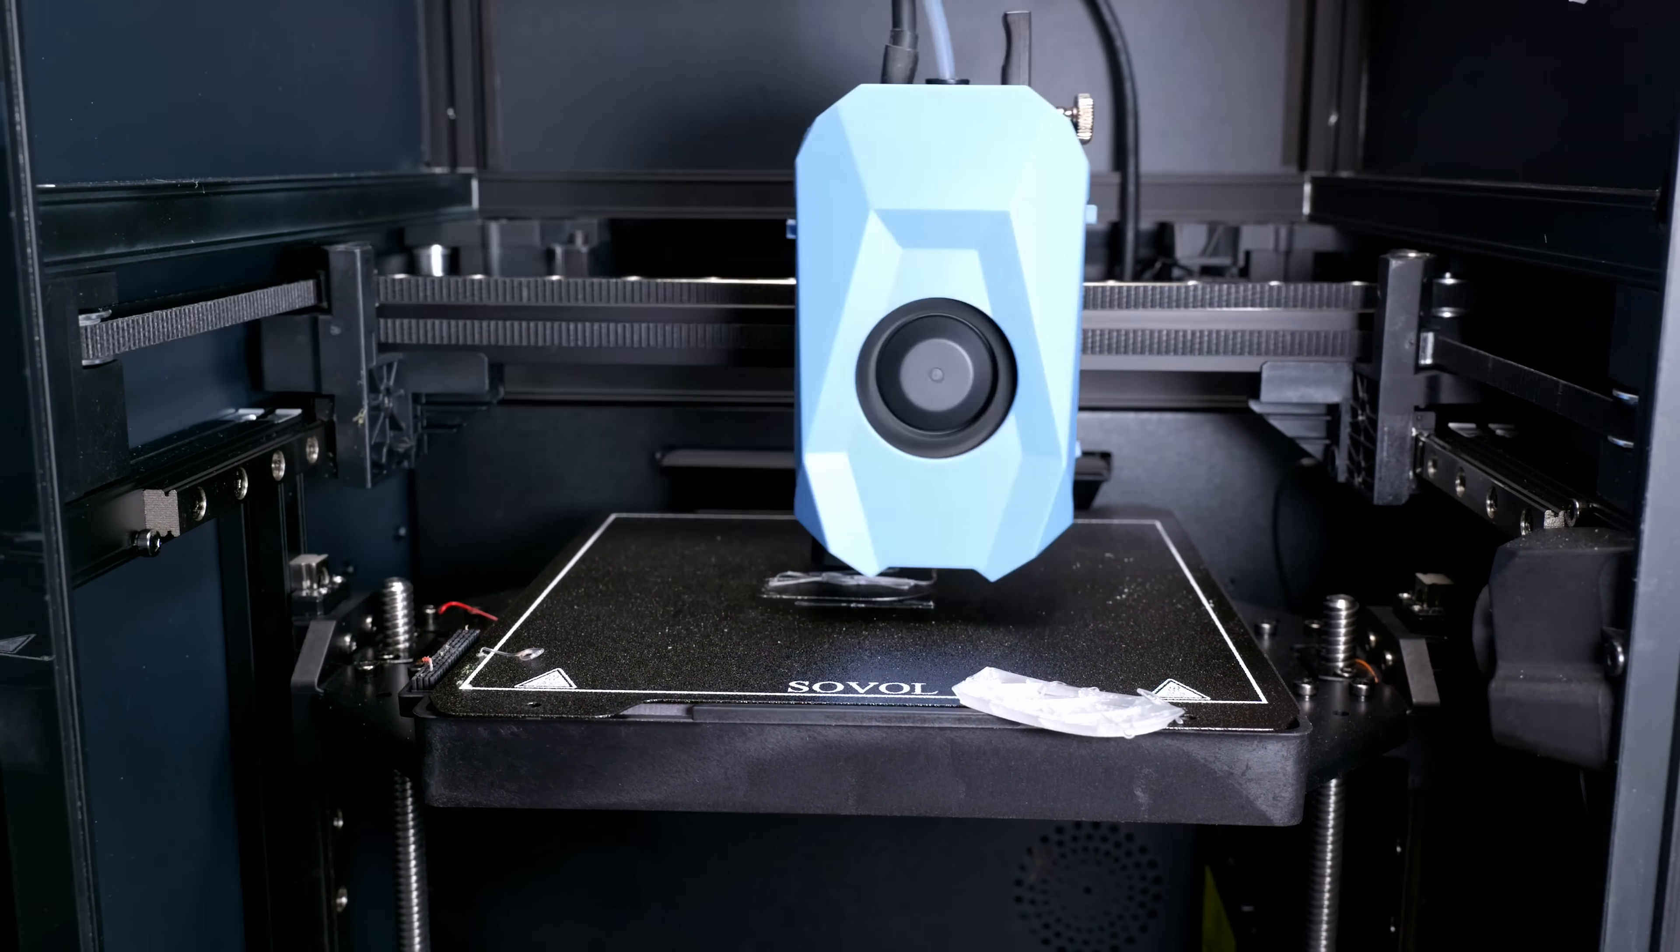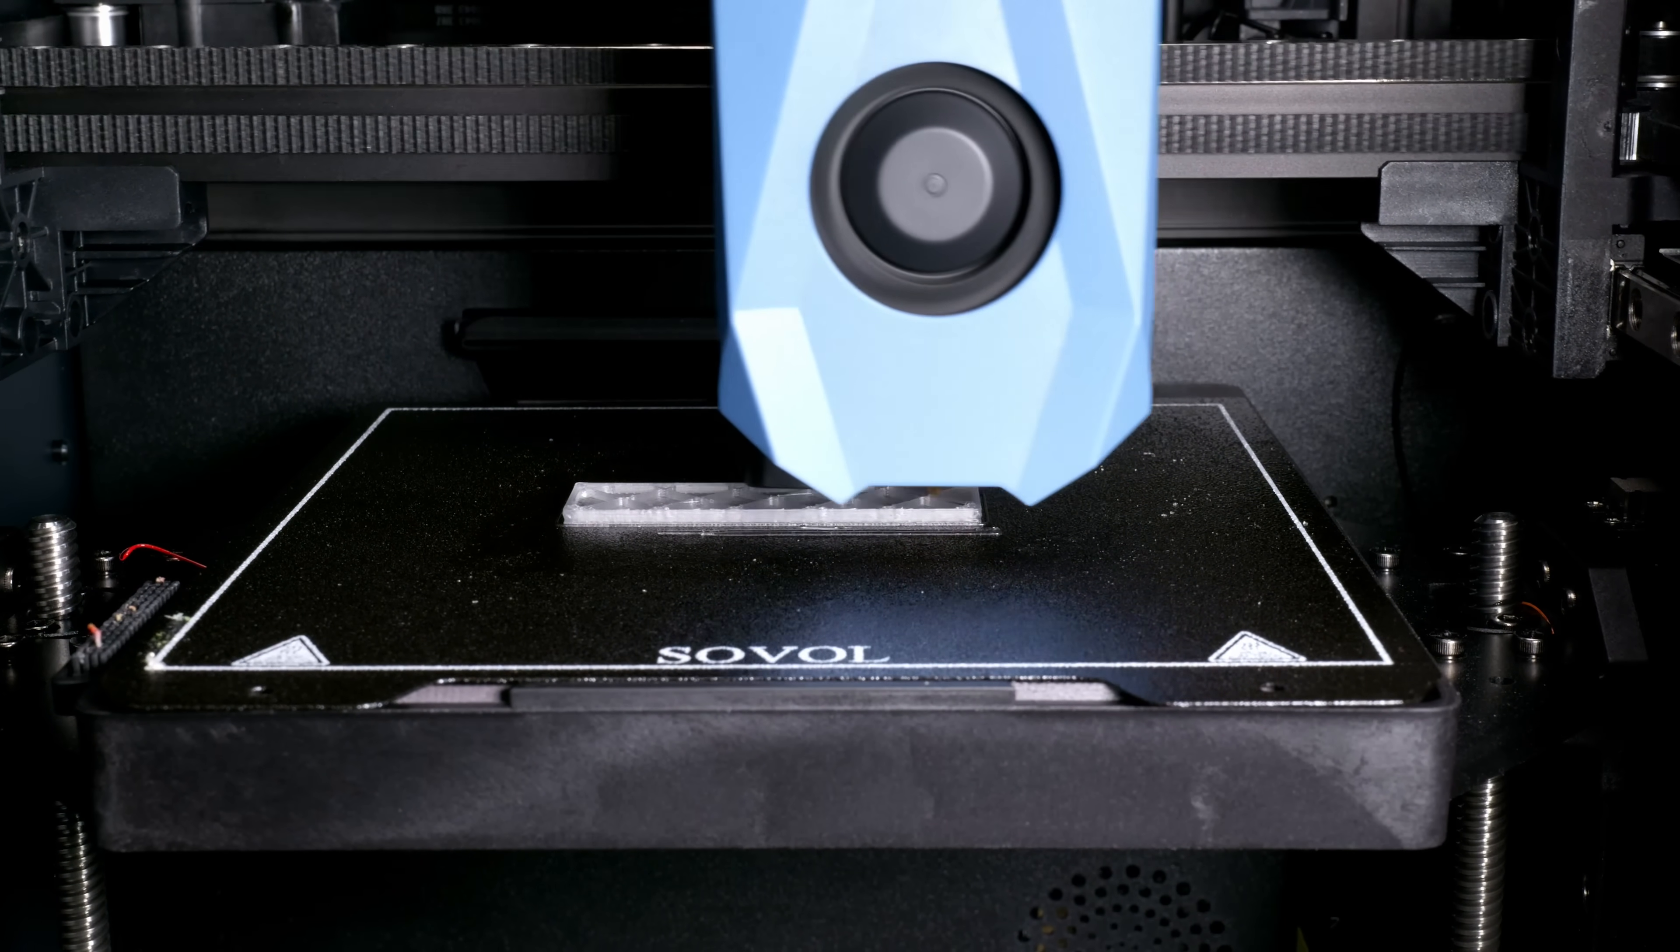Next up is something gooey? Magigoo. Magigoo isn't the only adhesive out there but I think it might be the only one that makes a specific blend for polypropylene which I think is important because judging by the colour hmm it's probably got PP in it. I mean it makes sense, polypropylene likes polypropylene. What this stuff enables us to do is look at another MSDS since we like doing that so much and well nothing spectacular really except the advice to use basic PPE which doesn't stand for polypropylene equipment it means gloves and spectacles cover your eyes apparently get this stuff in your eyes you're going to be having a bad time. The stuff did initially fail on the first try but that was because I forgot how much polypropylene really hates sticking to anything. It seems if you want to use it on a textured bed you have to get it on thick enough that it covers all the texture. It is that fussy. So I did that, I put a couple of layers on and I made sure it was nice and thick and then it works pretty well. It hangs around for multiple uses as well, it doesn't come off with the part and I think as a result it's probably slightly more durable than sticky tape at least in my experience. And it also is water soluble so you can wash it off with just soap and water.